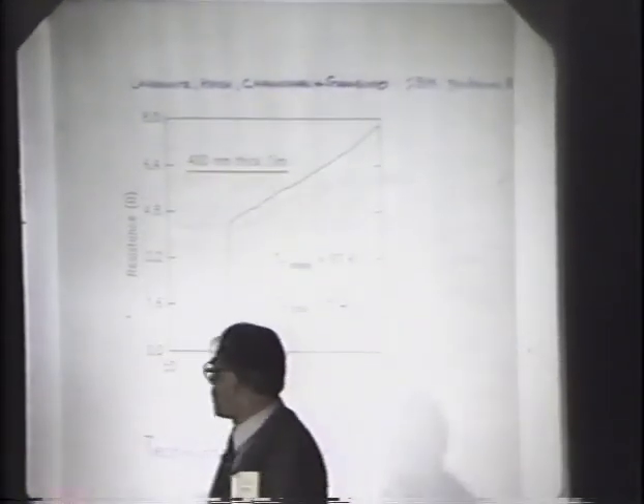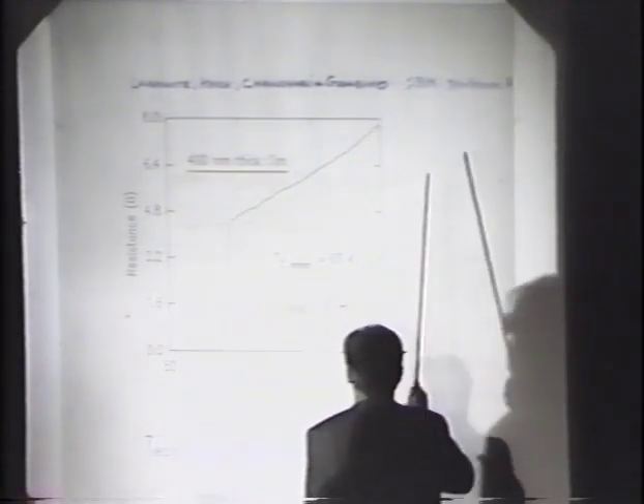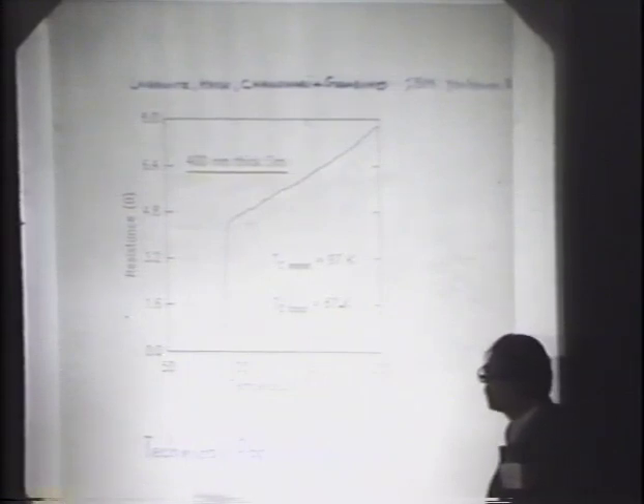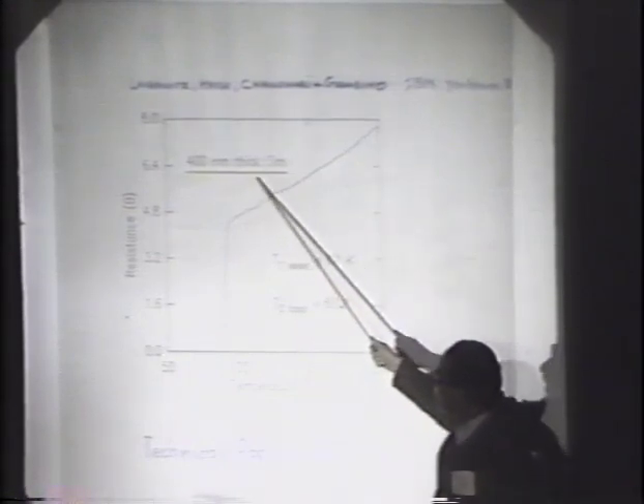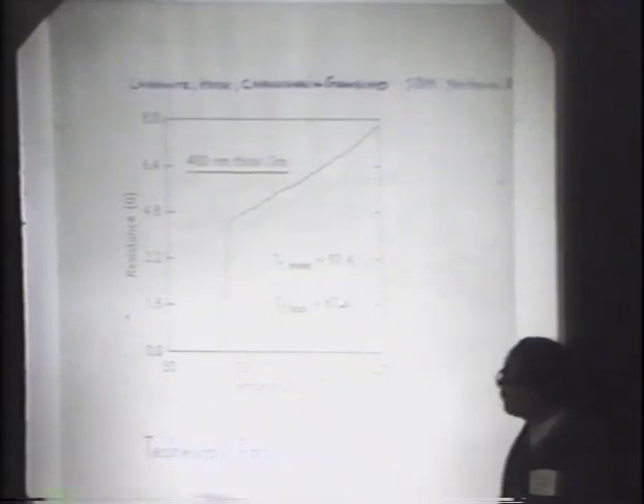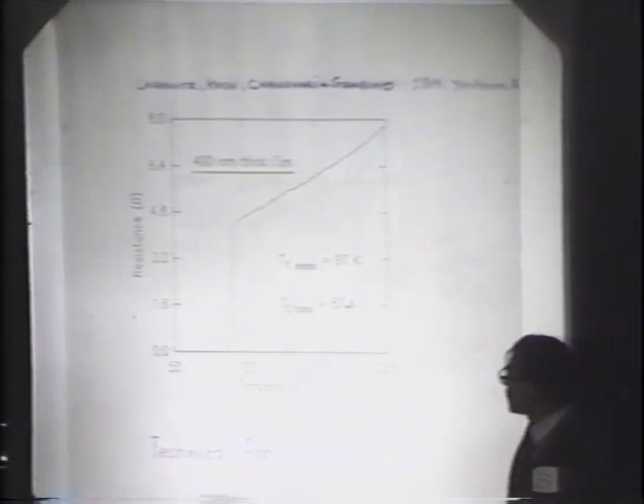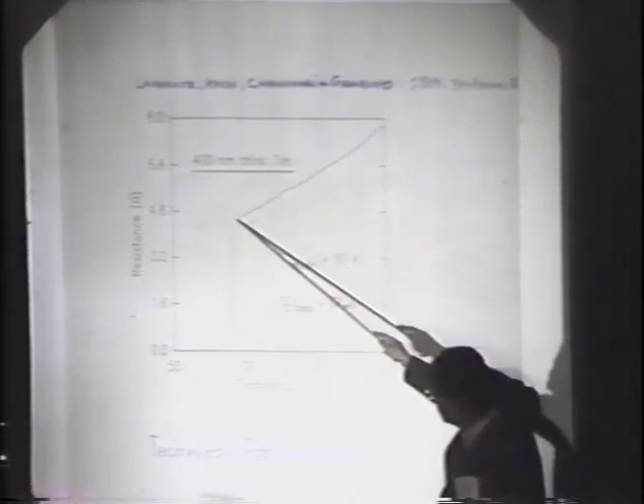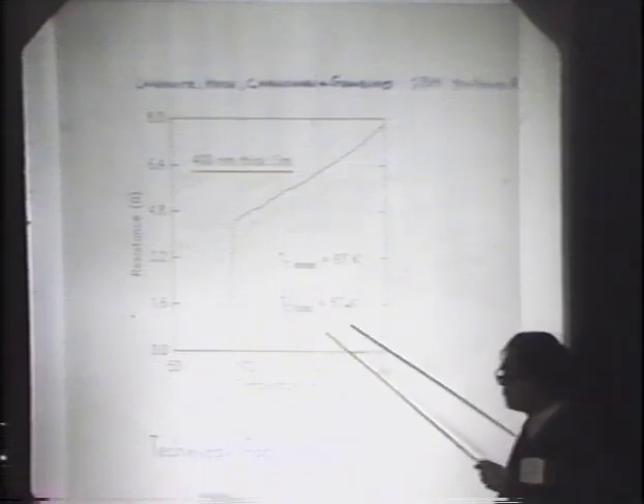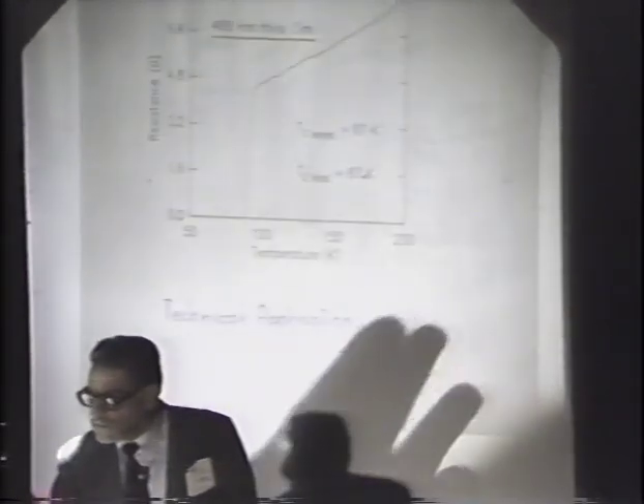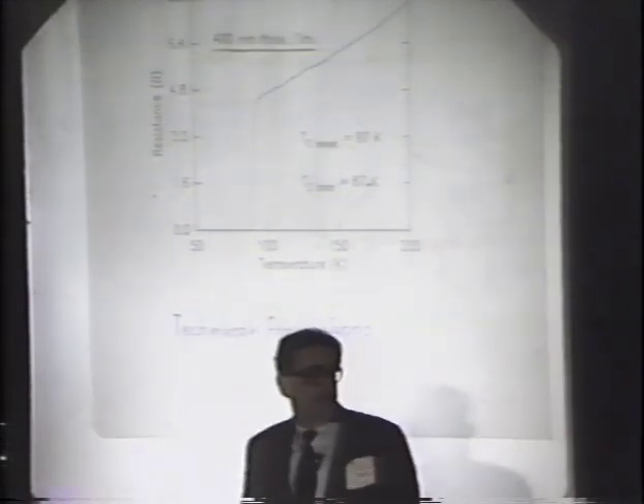And if you are interested in applications, then you may look at this result, which has been done at IBM Yorktown Heights over last weekend. It shows you the resistivity of a 400 nanometer thick film, which becomes superconducting at this temperature, and because it's a film, is proof that some technical applications are possible. And with this, I thank you for your attention.